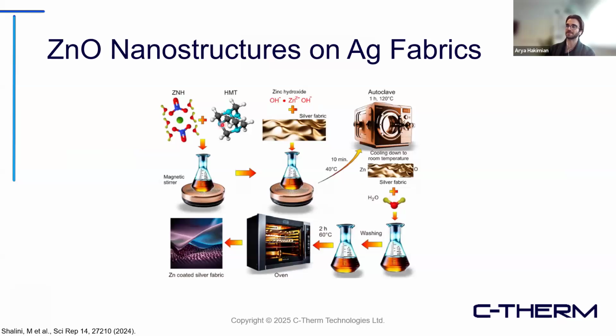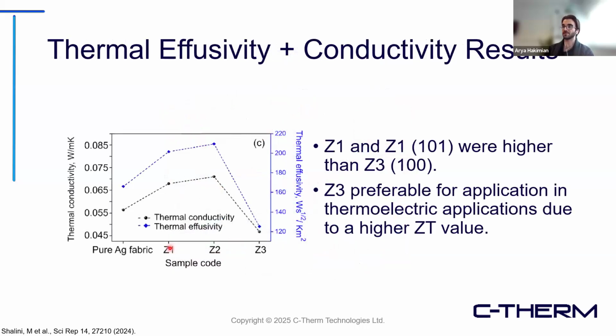I won't do the full breakdown here, but basically they were doing various concentrations of our two starting materials and introducing that onto a silver fabric. Through the process here, you can see, we get to the end, and you have a zinc-coated silver fabric, essentially. But depending on the ratio of the starting products, this would infer some differences in the type of zinc oxide that was produced on the fabric, and they were looking to see if that played a role in the overall thermal performance of those coated systems. And it turns out it did. So again, they provided thermal effusivity and conductivity as the main output here from their results. And I'll just say the targeted goal for this was to actually have the lowest value possible.